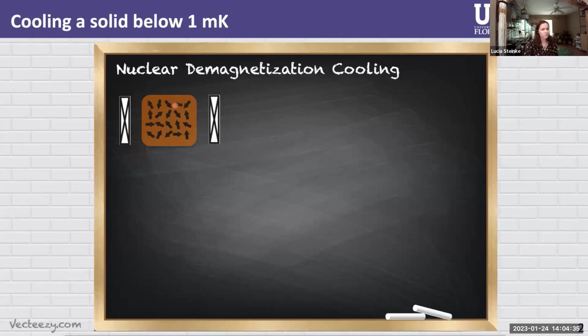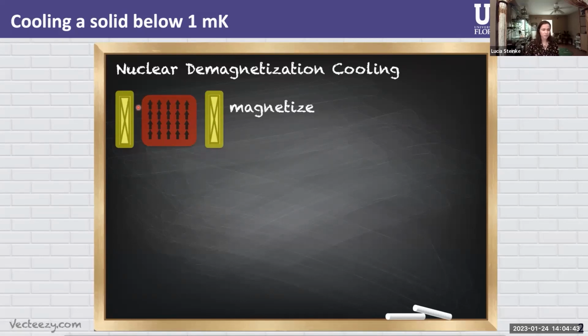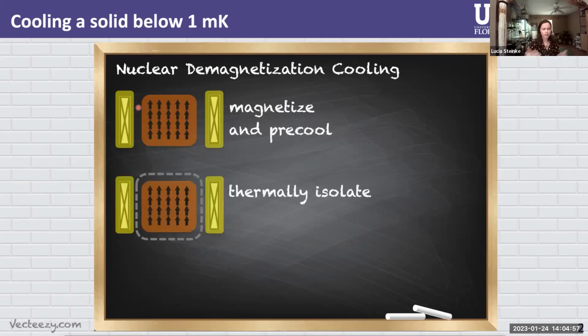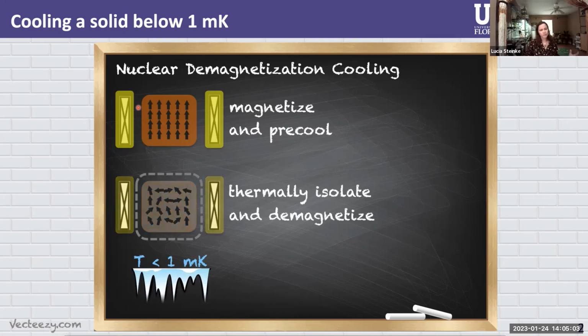That starts with a material such as copper that has nuclear magnetic moments. That's what we call our nuclear cooling stage. We apply a strong magnetic field to align the nuclear moments that removes entropy, which equals heat, from the nuclear system that gets dumped into the copper conduction electrons, and subsequently removed in a pre-cooled step by a closed cycle refrigerator. And now we're ready to completely thermally isolate the nuclear cooling stage, that's the adiabatic step, and slowly turn off the magnetic field. That allows the nuclear moments to become disordered again and soak up heat from the conduction electrons in the process. Using this technique, we can reach ultra low temperatures of 1 millikelvin and below and stay at these temperatures for weeks if needed.